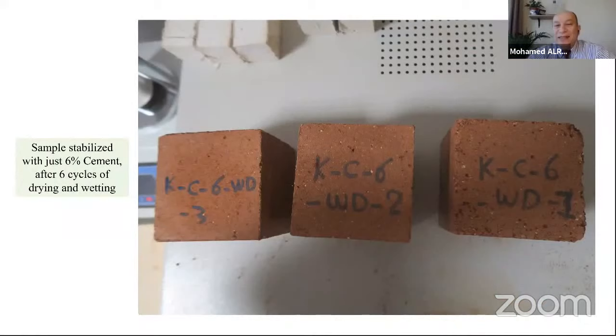And here is the worst part: we subjected those samples to drying and wetting cycles six times. What are drying and wetting cycles? We submerged the samples underwater for 24 hours. After that, we take them to the oven and increase the heat until we evaporate all the water and they become totally dry. And again we repeat this cycle. We submerge it in water and we dry it. We submerge it in water, we dry it. We do it six times. This is a very severe test, by the way.